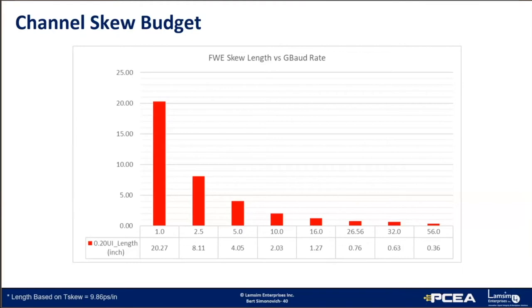At 16 gigabaud, which is PCIe Gen 4, the skew budget is 1.27 inches. At 32 gigabaud, Gen 5, it's 0.63 inches. And at 56 gigabaud, which is the baud rate for 112 gigabit per second, it's only 0.36 inches, a little over 1/4 inch. That's not much margin. You may need to pay more attention to these links.